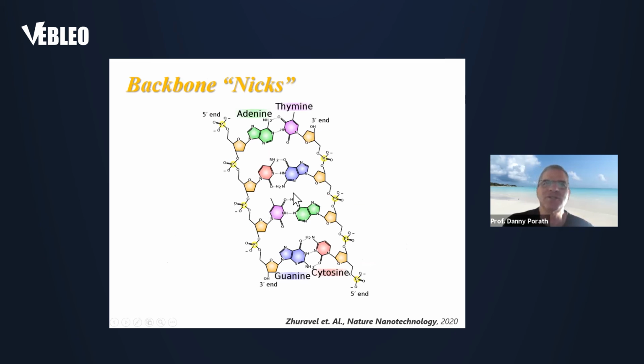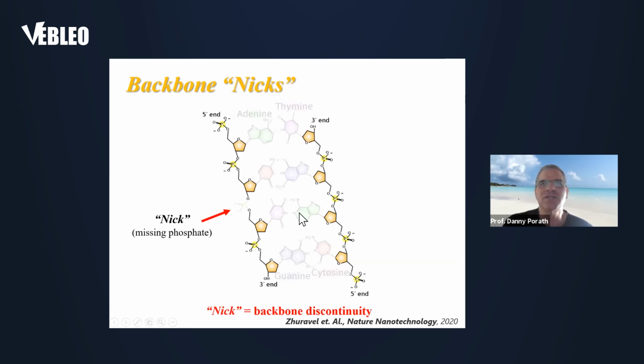So again, when we look at the structure of the DNA, we can see the backbone and the bases. And in order to check if the backbone is conductive, we can simply cut it. Cut it means that one phosphate is missing. This is called a nick in the backbone. If we make a discontinuity in the backbone, current shouldn't transport in the backbone. And if the current is going through the bases, we would expect current to flow even in the presence of a nick. And if the current is going through the backbone, then the cut will reduce the current.